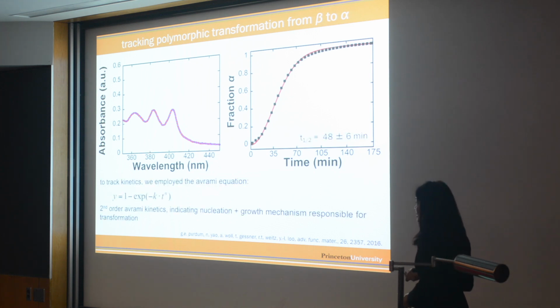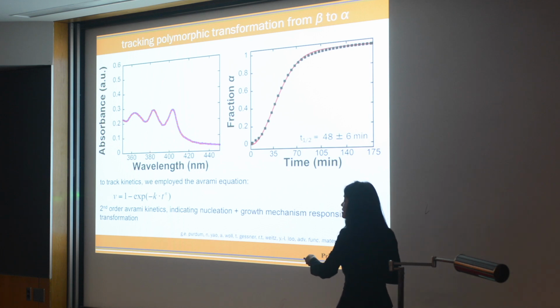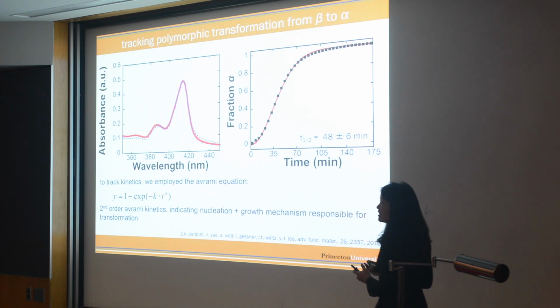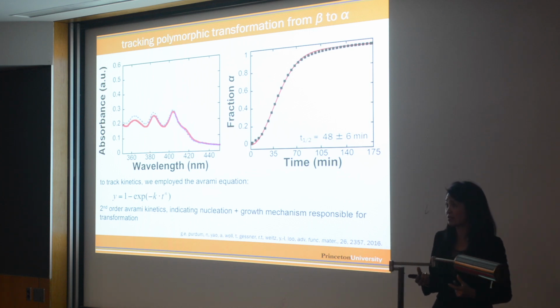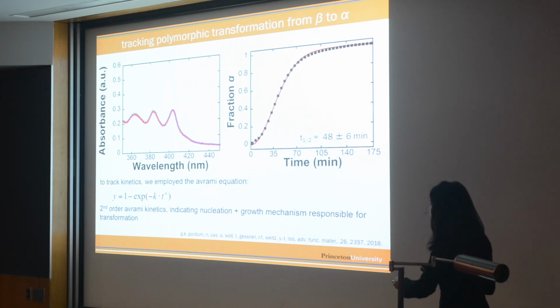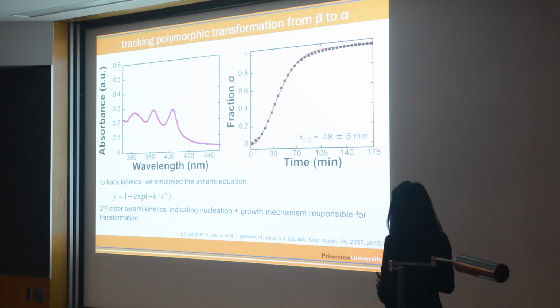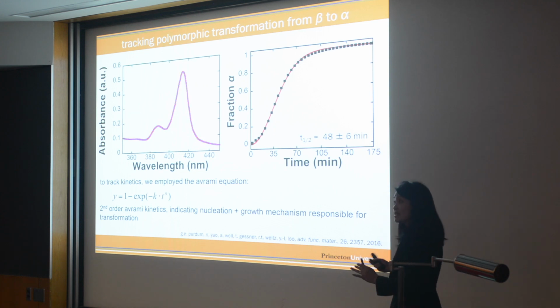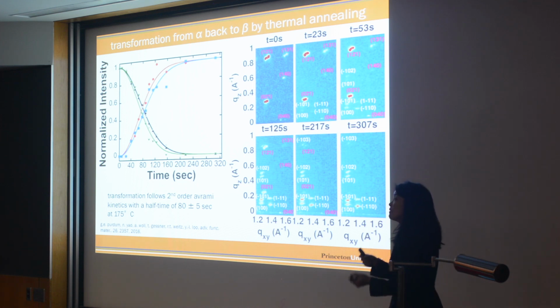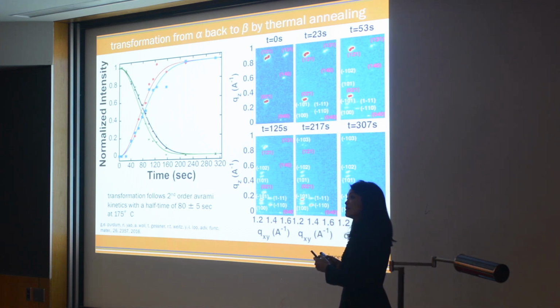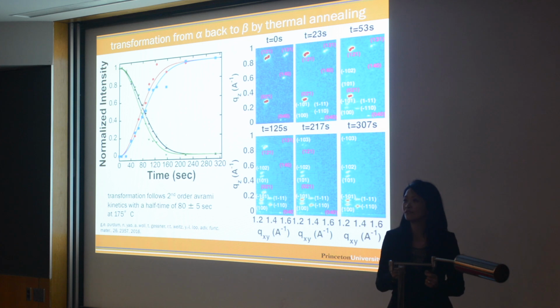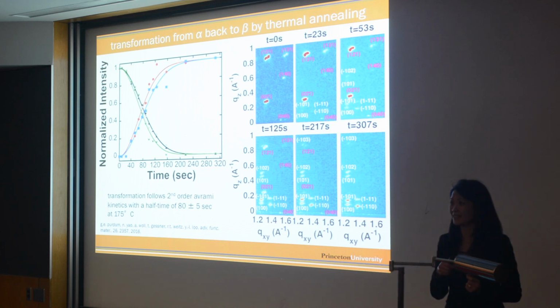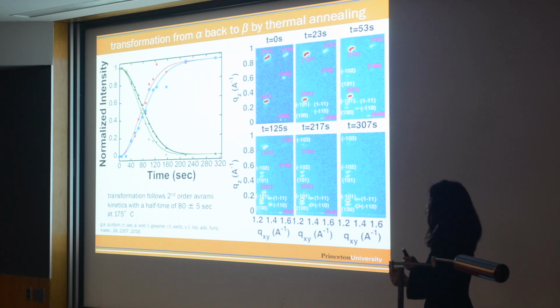We can fit this kinetic data, and it turns out it fits nicely to the Avrami equation. We get a second order of Avrami kinetics that tells us it's a nucleation and growth process. I'll come back to this nucleation and growth process in a little bit. Suffice to say, we can quantify this process. It turns out that now that you can get to the alpha phase, if you thermally anneal this alpha phase, you can get back the beta phase. So these polymorphs are reversible. You can go back and forth, back and forth.